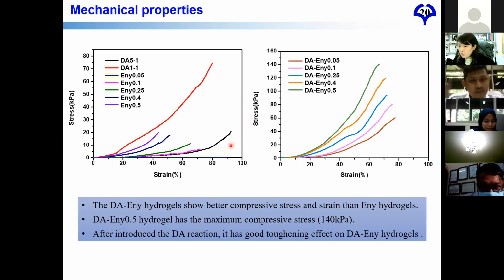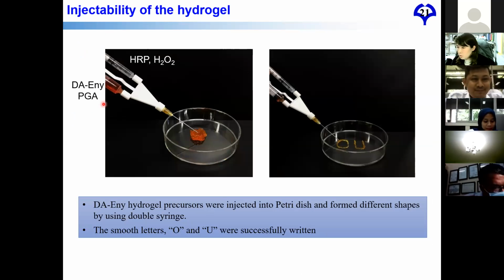Okay, we can also control the stress of the hydrogel by the concentration of the enzyme. Using this kind of hydrogel, you can see that we can use a double syringe to inject it. One syringe has only the DA and enzyme PGA, and the other syringe has the HRP and H2O2. During the injection, the HRP and the PGA mix together and become the hydrogel very fast. So we can also write the smooth letters O and U very successfully.